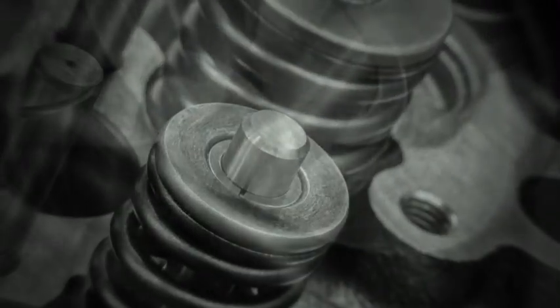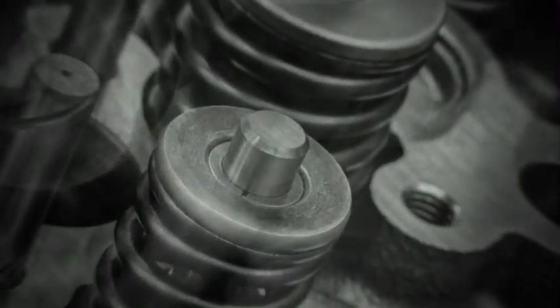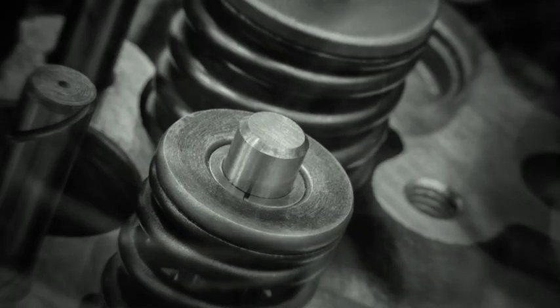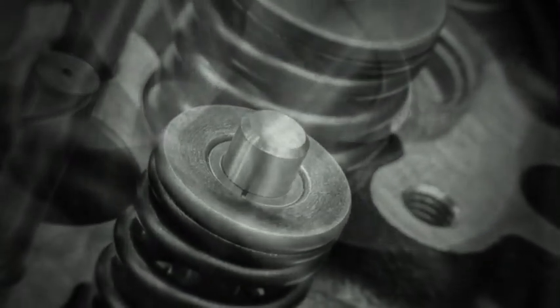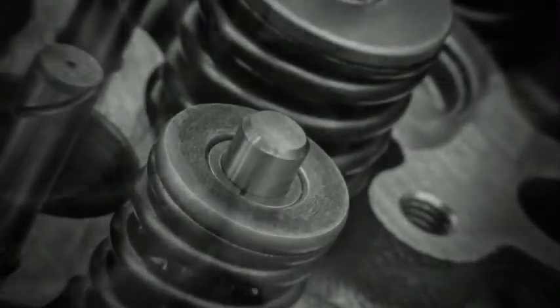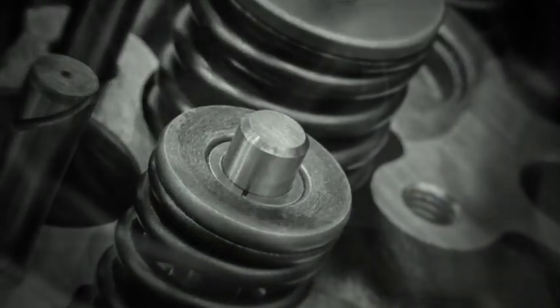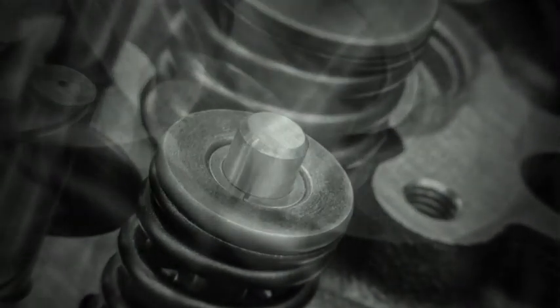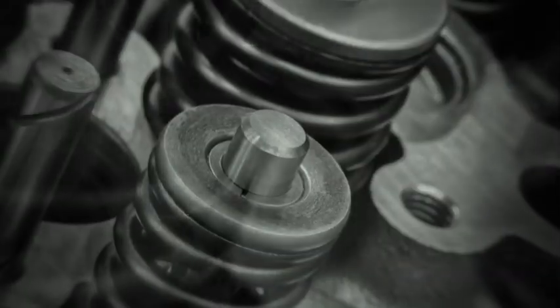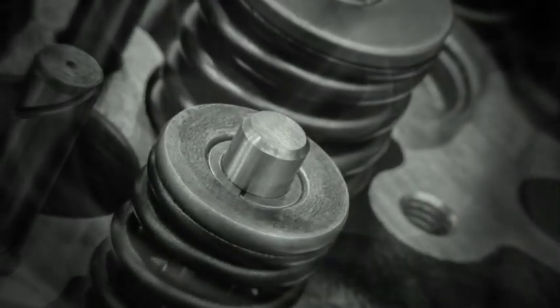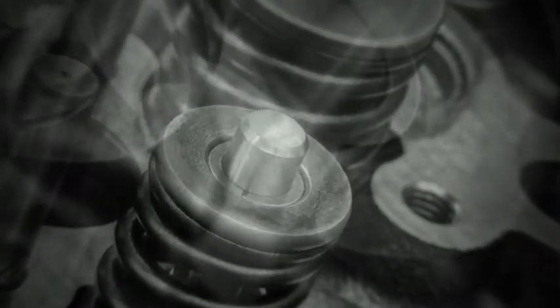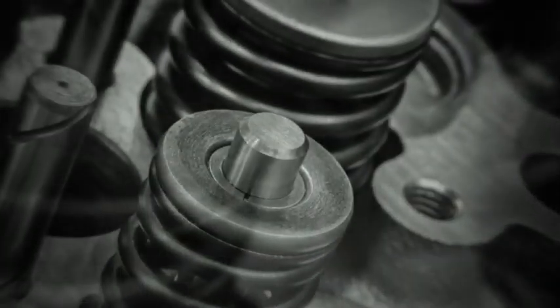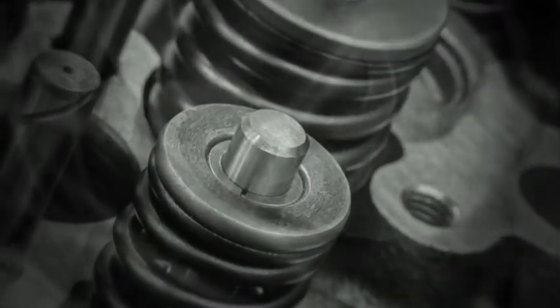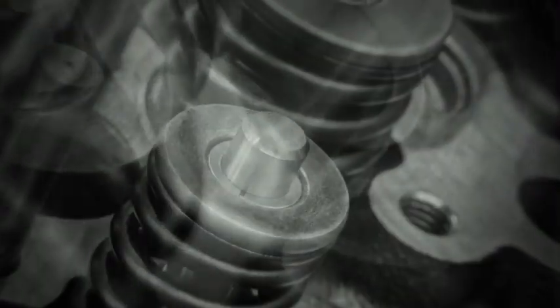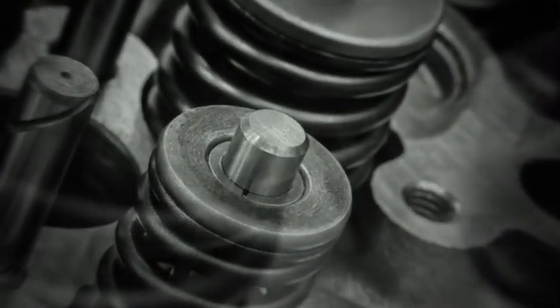A fatigue fracture often contains a relatively smooth region where the crack grew, and a rougher final region where the remaining material failed suddenly. The origin may be a tool mark, corrosion pit, seam in the wire, grinding burn, decarburized area, or contact scar. Spring design uses stress range as well as maximum stress.